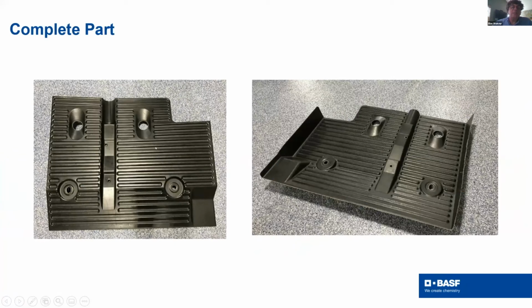And as you can see, it's so beautiful, of course, because we really modified the spray to really impregnate on those edges. And you can see how it is well trimmed on the trim edges. This is all in one cycle, and that's the beauty about that. You can get the high strength, add features into it, and yet get one cycle. With that, this is a big part, and you can see it has complex geometry, lots of geometry features in one cycle.